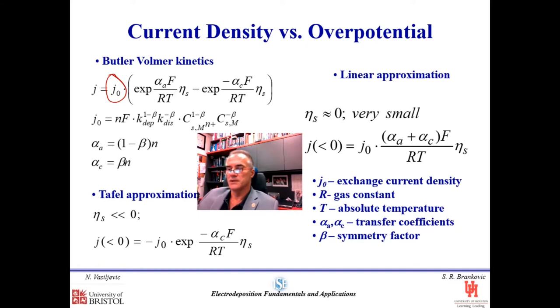The transfer coefficients are defined in terms of the symmetry of the energy barrier for charge transfer at the electrode surface, and they're defined here. This is pretty much all I would say about those terms, but a more elaborate description you can find in any textbook. Butler-Volmer kinetics is a hyperbolic sine type of relation which could be approximated. One of the approximations is the Tafel approximation for very large overpotentials. We can basically use the exponential dependence only of the term that is showing the cathodic coefficient. If we are talking about smaller overpotentials, then we can use the linear approximation, which is shown here, where the current density and overpotential have a linear relation.